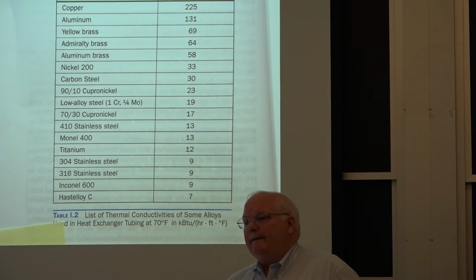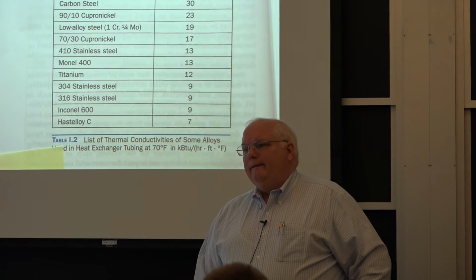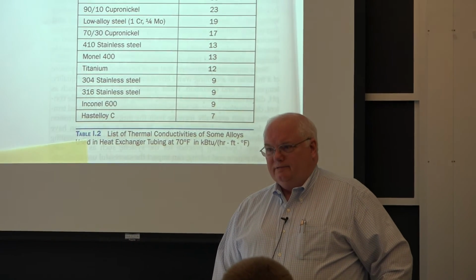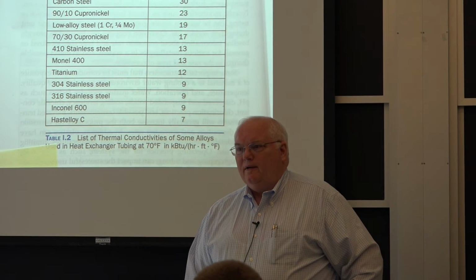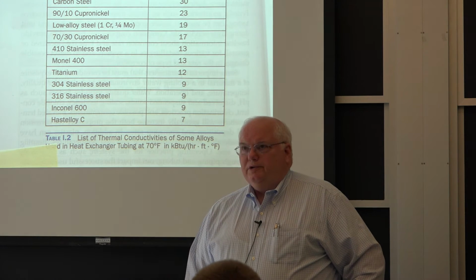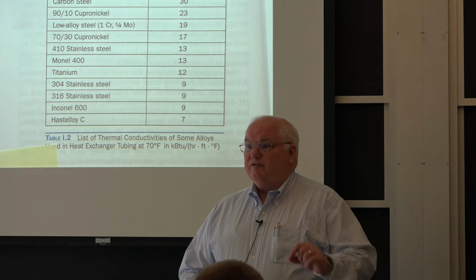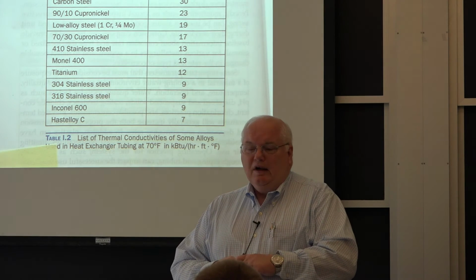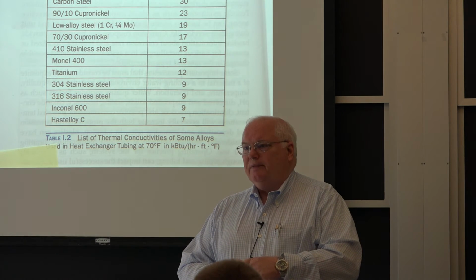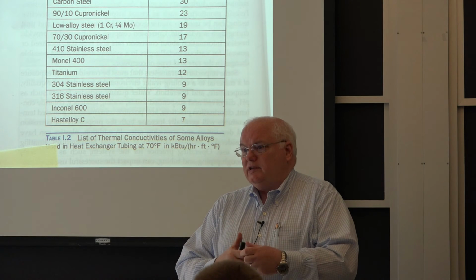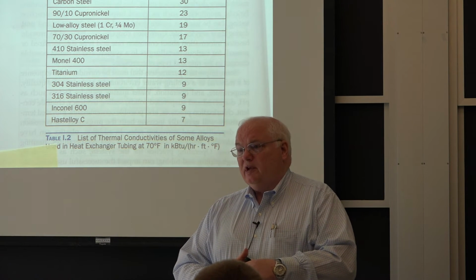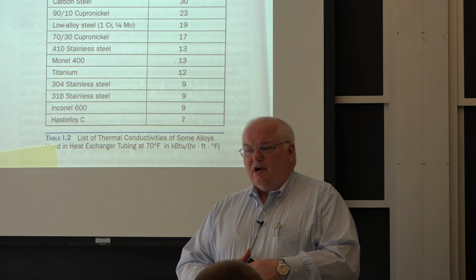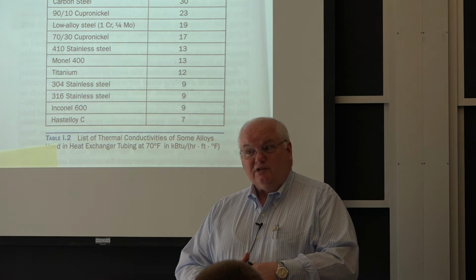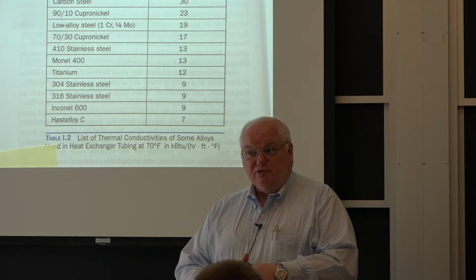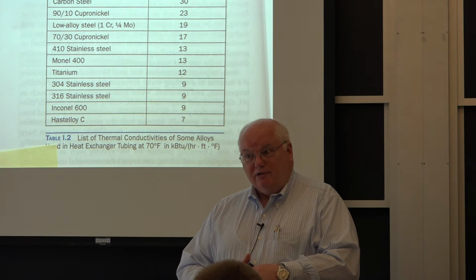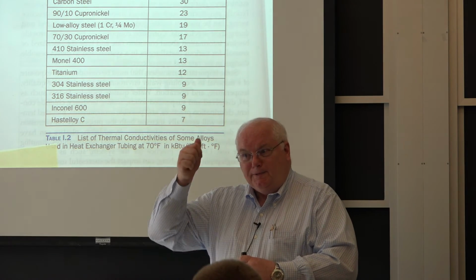Yes? So do you get better thermal conductivity in titanium since the walls, I assume, would be thinner than the other ones? Yes. The conductivity coefficient's lower, it's still better. Because it doesn't corrode and you don't have to have extra corrosion allowance on your thickness, you can use half the thickness, okay? It's also stronger, you can use less thickness. Maybe you even use a third of the thickness in some cases, but you're talking about material that's going to cost you $70 a pound as opposed to $7 a pound as opposed to carbon steel at 70 cents a pound, okay? So the price is, yep.